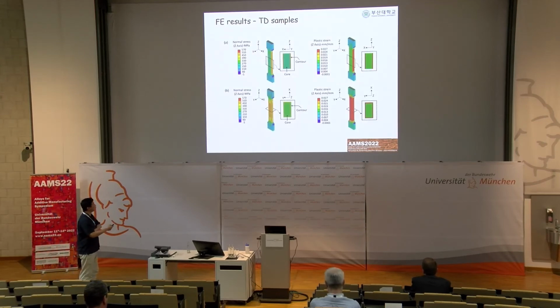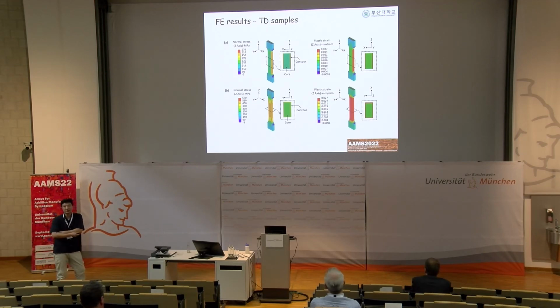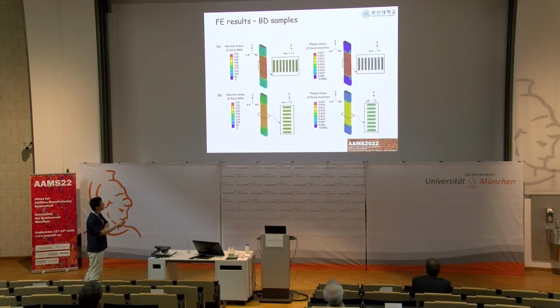And here's actually the reason why we have the size effect. If we look at the finite element result, the core contour region is slightly stronger in yield strength. While we apply the tensile load, this is where stress is concentrated, but in this case the effect is not really strong. While we are increasing the surface area, the portion of the strong material becomes larger and larger, and then influences the overall properties.